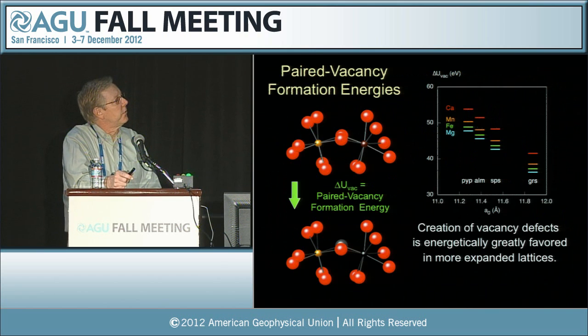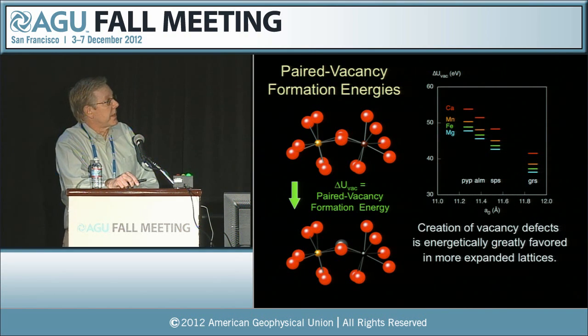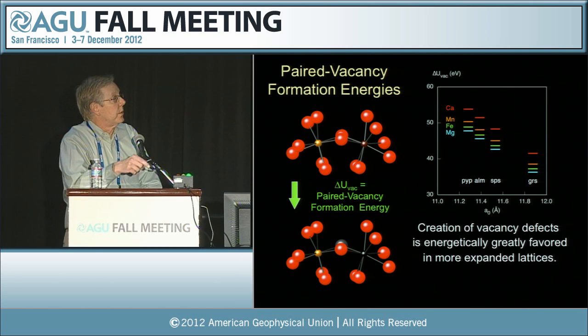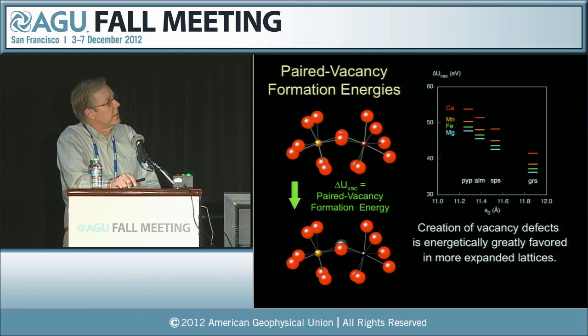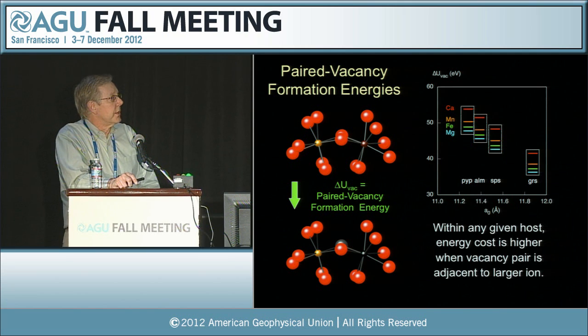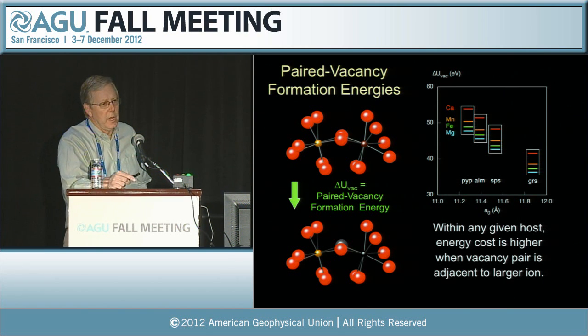Looking at the paired vacancy formation energies, again plotted in exactly this same fashion, this is a marked effect, and we can see that the creation of these vacancy defects is energetically greatly favored in these more expanded lattices that you see here, grossular on the right. And in addition, if we look within any one given host, you can see that the energy cost is higher when the vacancy pair is adjacent to a larger ion.